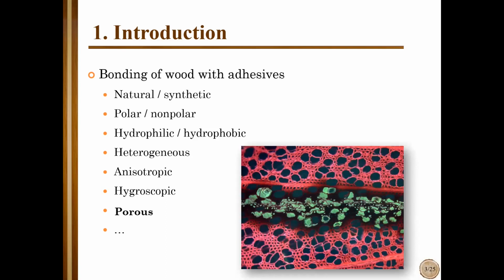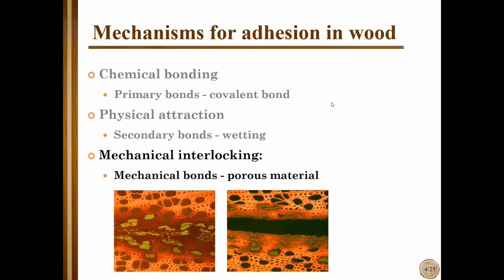So wood is porous material, and this porosity plays a quite important role in adhesion. Main mechanisms for adhesion in wood are actually chemical bonding, physical attraction, and mechanical interlocking. Today, I'm going to focus on mechanical interlocking. This is related to porosity of the material. So adhesive penetrates into lumens and cracks and other pores in wood. And then when it hardens, it presents kind of mechanical bonds, anchors. And this way it holds together two pieces of wood or veneer or other wood particles.